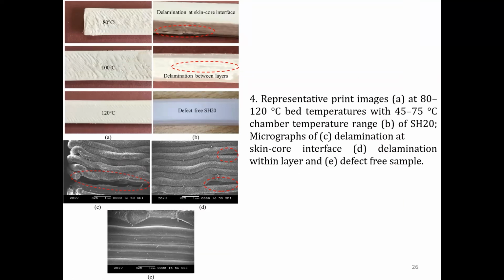So we need to set an appropriate chamber temperature as well to reduce the temperature gradient, which will affect this delamination. As seen from 4B, below 75 degrees C chamber temperature, delamination is observed at the skin core interface and within the layers also. The visual observation after printing and the micrograph as presented in C, you can see here a nice micrograph. These are the layers, and you can see the delamination here. This is the skin and this is the core. This core is a foamed one. So these are many of the parameters which creep in when you go for multi-material systems. And thereby we need to really look for a micrograph, something like this, which is definitely possible with patience, and with some extra amount of time, it can always be possible to navigate to a best sample.